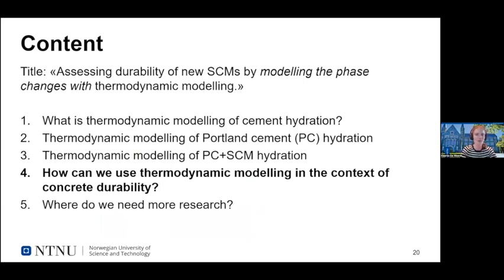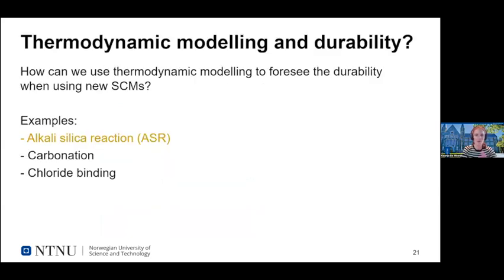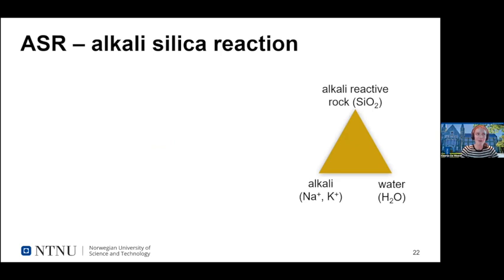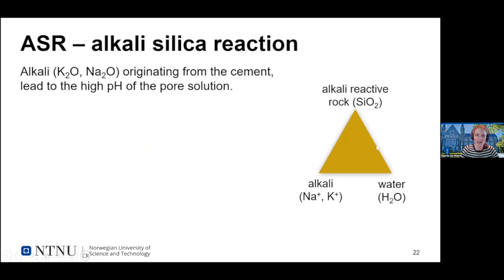So how can we use this in the context of concrete durability? What I'm going to do is give 3 brief examples of how we've used thermodynamic modeling to look at durability. But there's much more. But for the sake of time limitations here, let's look into these 3 examples. So we focus first on alkali silica reaction, or ASR, and a very brief repeat of what ASR is. So we need alkali originating from our cement, and they lead to the high pH of the pore solution, as we just saw.